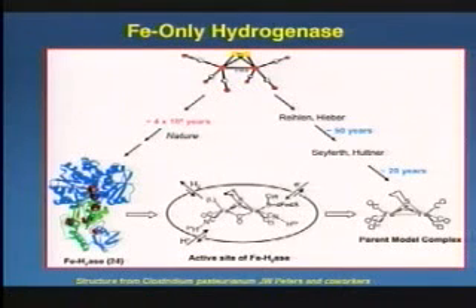The catalysts are equally important, because if we don't avoid noble metal catalysts, we'll never get the cost point down to fuel. As I said, we know nature does that. We only now know that nature's hydrogenases use either nickel or iron. All fuel cell catalysts, by the way, that are hydrogen fuel cells, the low temperature ones, are poisoned by sulfur. And you'll always hear people say how pure the hydrogen stream is needed in order to keep a fuel cell working at low temperature. But nature figured that out. In fact, they're also poisoned by carbon monoxide. And the natural molecule is a diiron compound that actually incorporates in it both carbon monoxide and sulfur. So it's not poisoned at all.